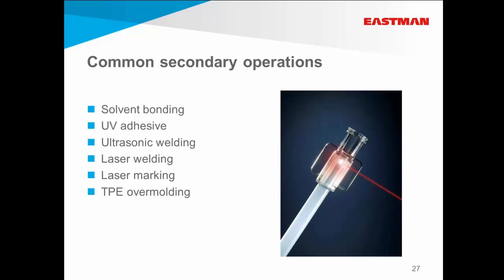The solvent itself, typically one of the more common ones is called cyclohexanone, can be very aggressive towards some of these engineering plastics. In the case of the Triton copolyester, there's not a chemical attack per se, but you do get really good high bond strengths with the tubing and the rigid material. So that typically means you have a much better device. You don't have to worry about the pull strength of the luer being pulled off the tube. You will get tubing failure before you get bond failure.